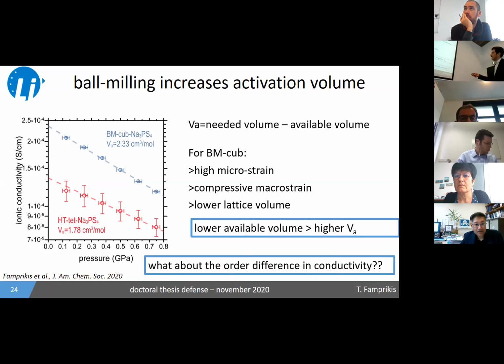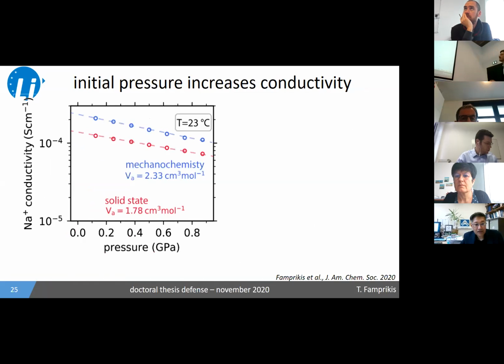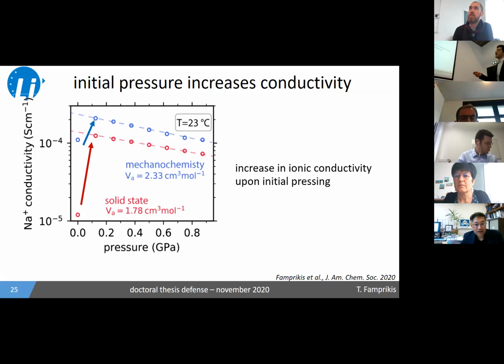Let me just plot the same data here with an expanded Y scale. And I can show like this the initial points of conductivity measured in the same setup, but before we apply any pressure to the materials. And you will see quite a big difference, deviating from that straight line of the activation volume. So basically what we see is that for both samples, we have an increase in ionic conductivity upon the initial pressing,